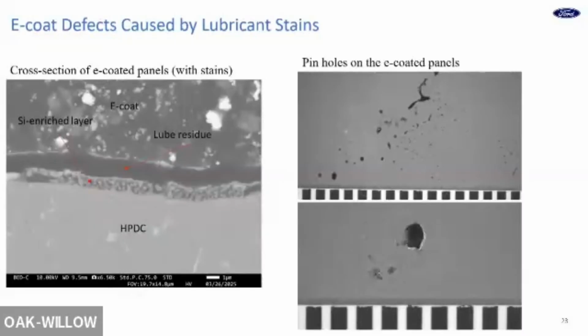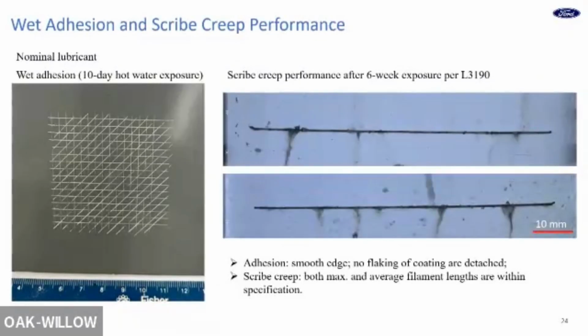So in certain conditions, it can affect the adhesion. If the staining is very thick or very heavy, it may leave some pinholes on the surface. That means there is no e-coat formation on this area, so potentially some lower corrosion performance. We also looked at the e-coat performance. With the nominal lubricant, the wet adhesion is actually very good, and also the scribe creep performance is all very good. So they all meet the current specification.